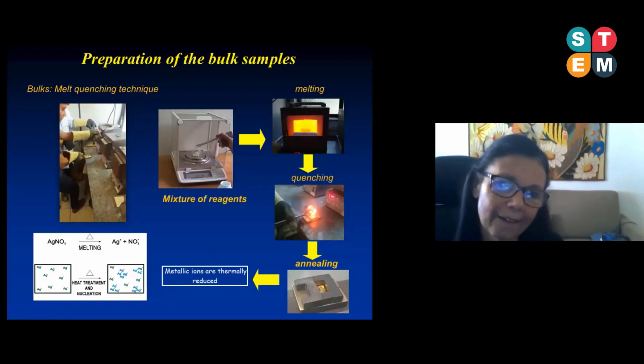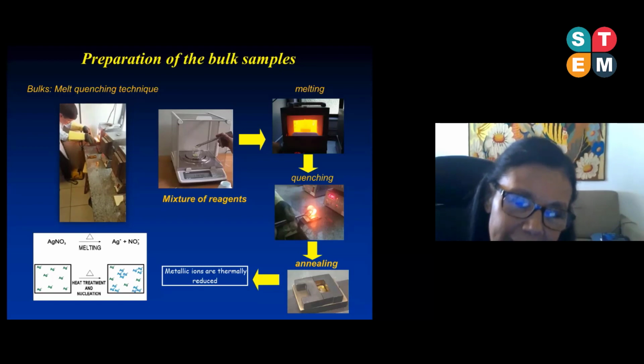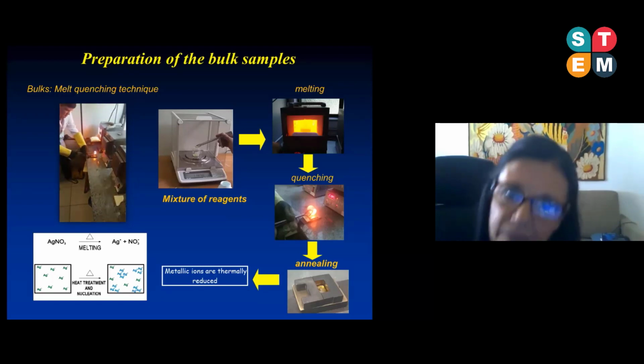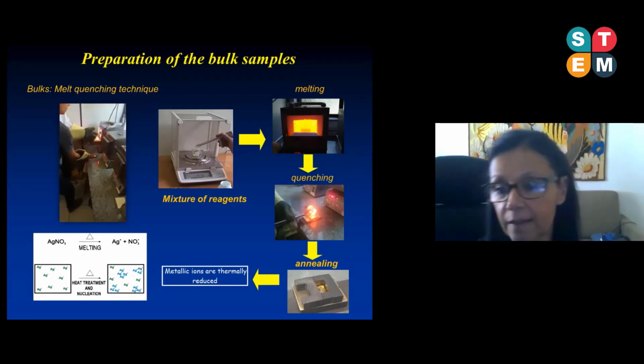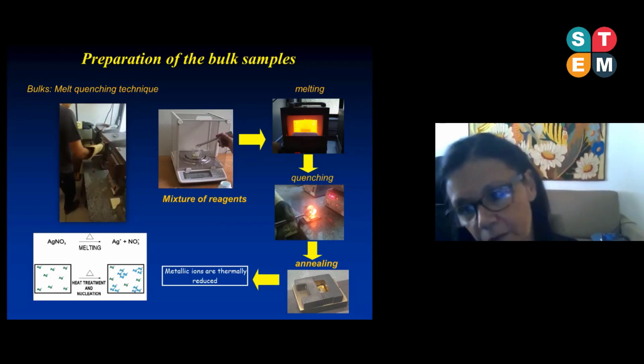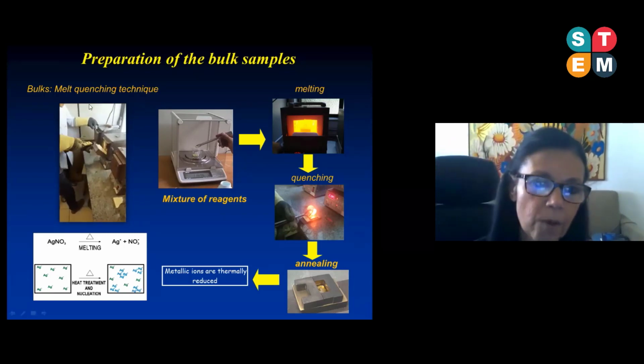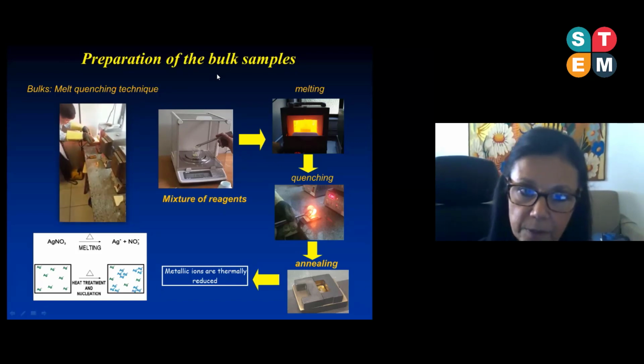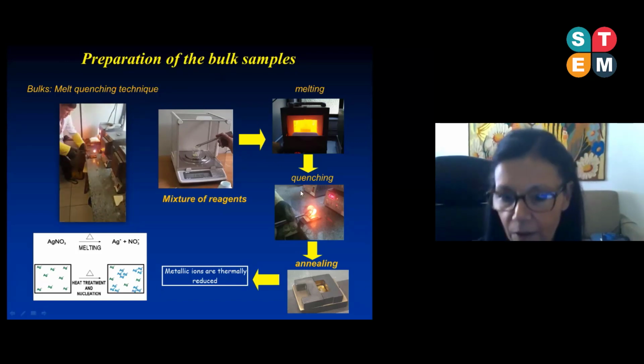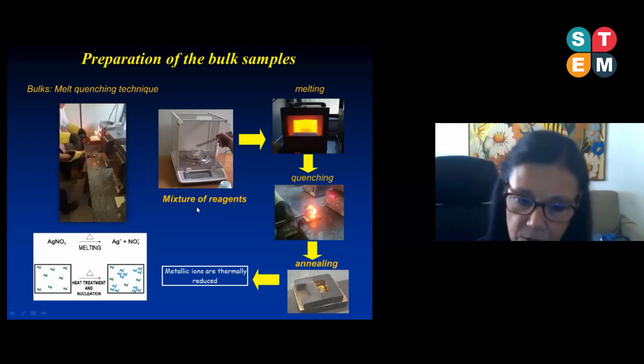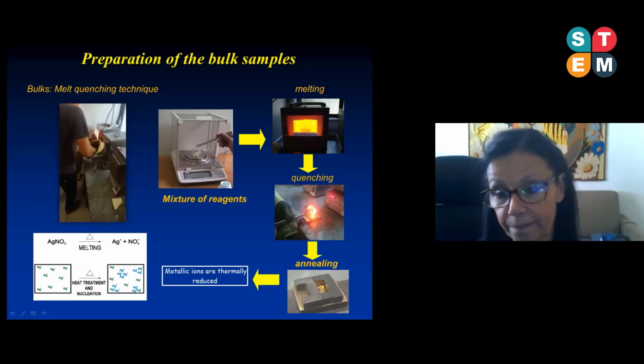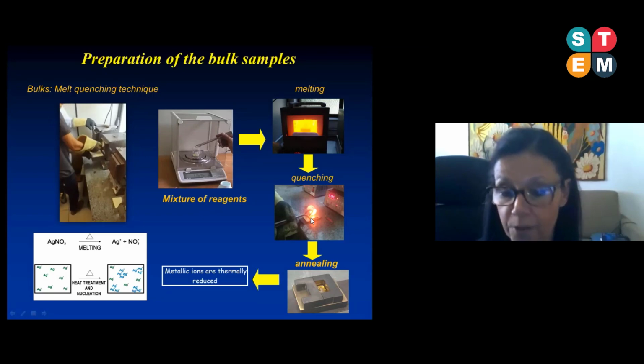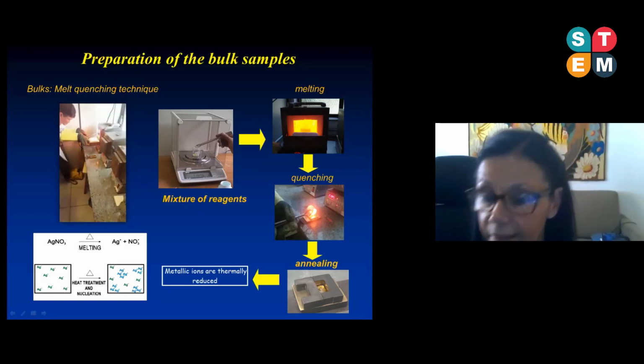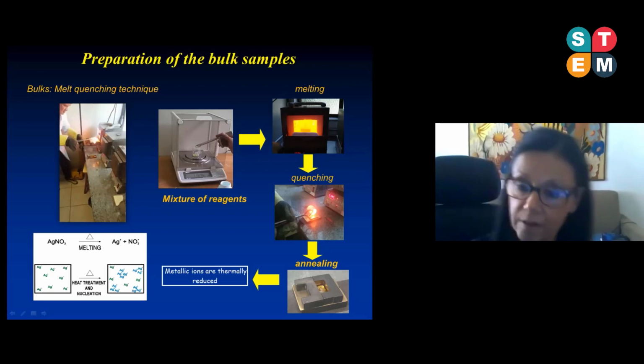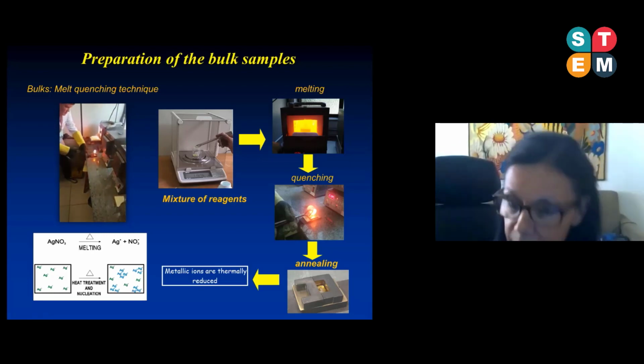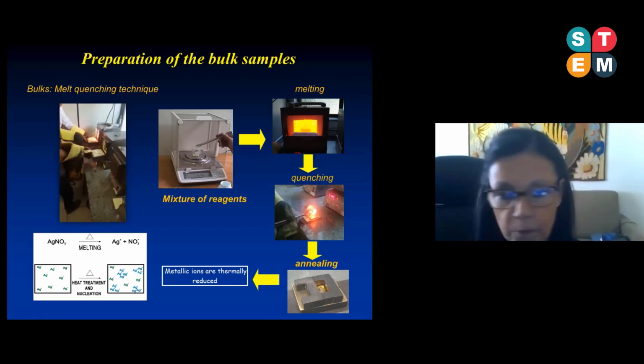Well, now I'm going to show you very quickly some of these results obtained in bulks and that motivated the research with the optical amplifiers. We use the well-known melt quench technique to prepare these bulks, whose steps are shown here. First of all, we have the mixture of the reagents, after that the melting, the quenching in a preheated brass mold, and finally the annealing. The annealing is performed to reduce internal stress and also form the metallic nanoparticles by thermal reduction.